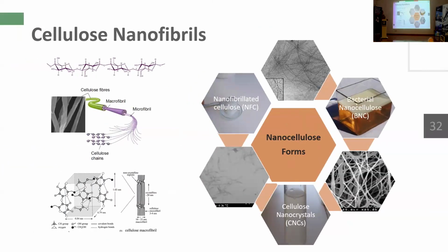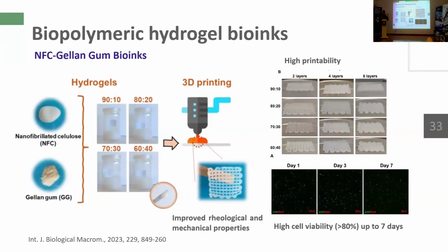Here, regarding nanocellulose, we are working essentially with nanofibrillated cellulose that is obtained by mechanical and enzymatic treatment of plant fibers. I will not go into detail, but you see that we have these isolated nanofibers, and this nanocellulose is essentially used as reinforcement to improve the mechanical performance and rheological properties.